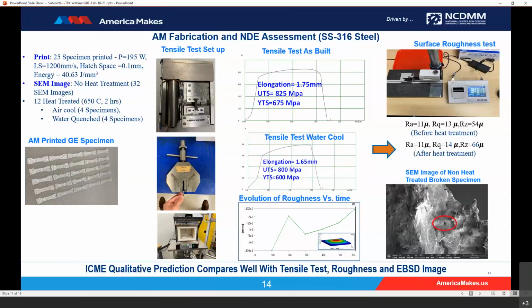And as you can see in this particular case, we printed 25 specimens with the powder, and they were 20 layers thick. Each layer was, I believe, 40 microns, so the total height was about 0.8 millimeters. Of the specimens, 12 were subjected to heat treatment at 650 degrees Celsius for 2 hours. Of that, 4 were air-cooled and 4 were water-quenched.